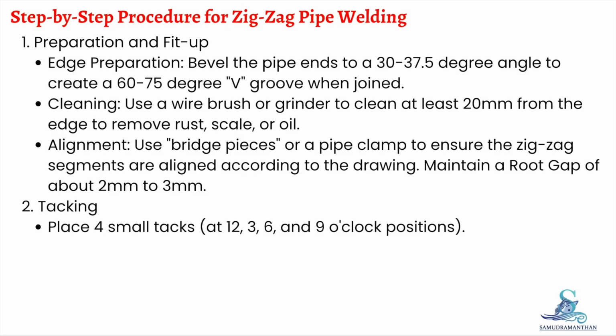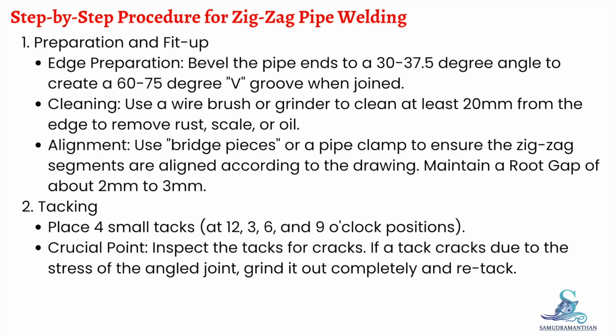Tacking: place 4 small tacks at 12, 3, 6, and 9 o'clock positions. Crucial point: inspect the tacks for cracks. If a tack cracks due to the stress of the angled joint, grind it out completely and retack.